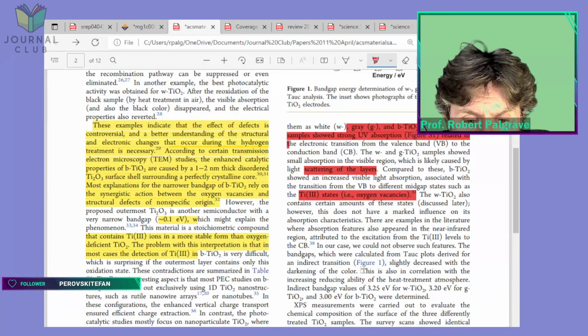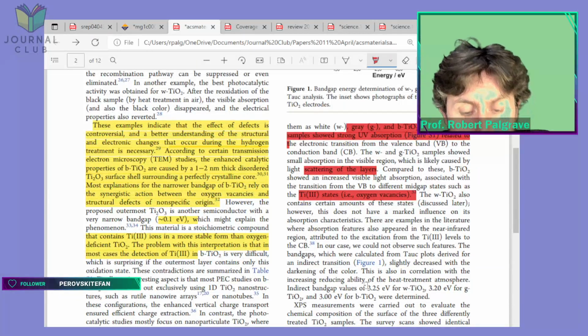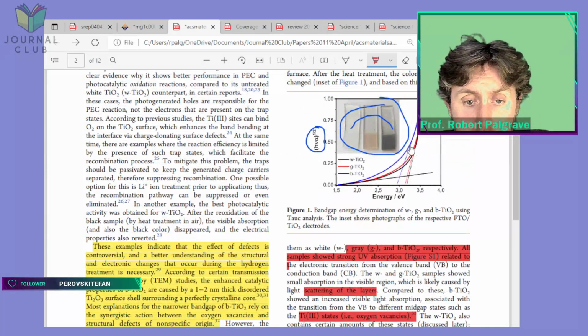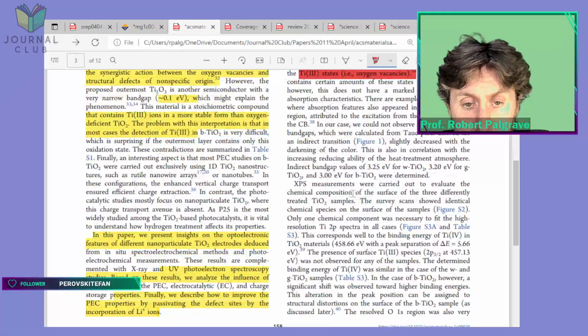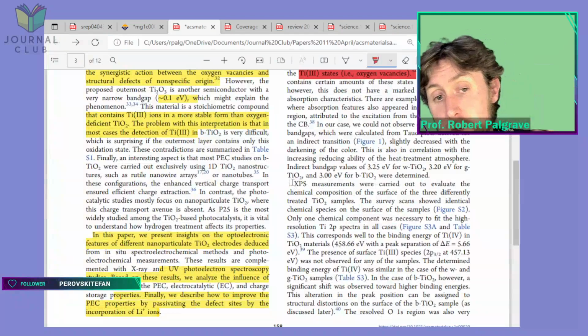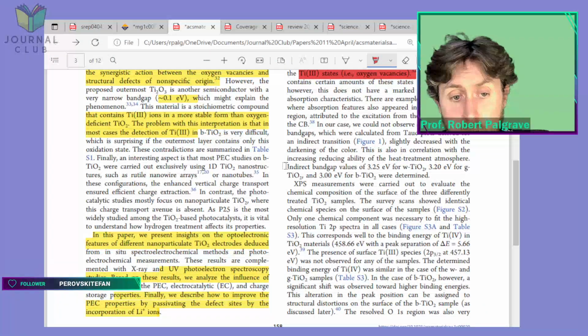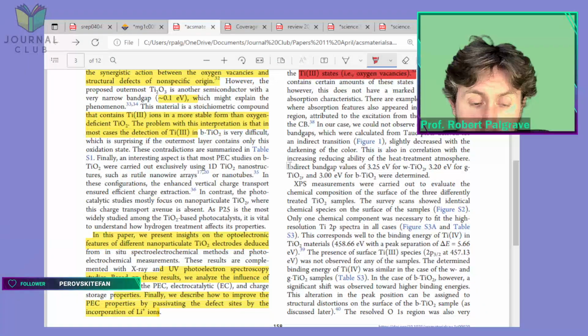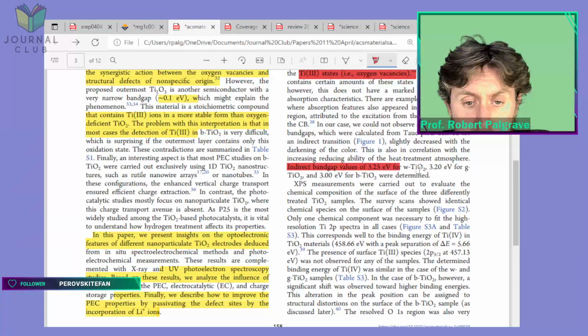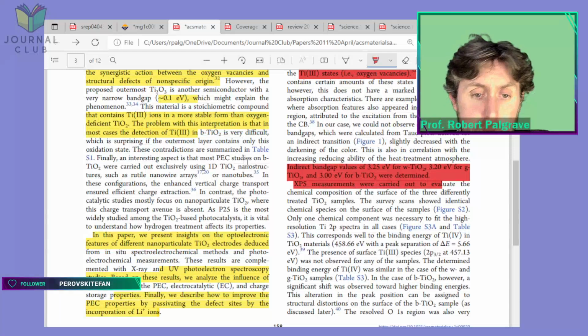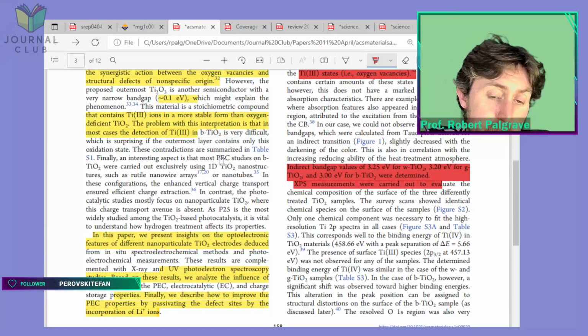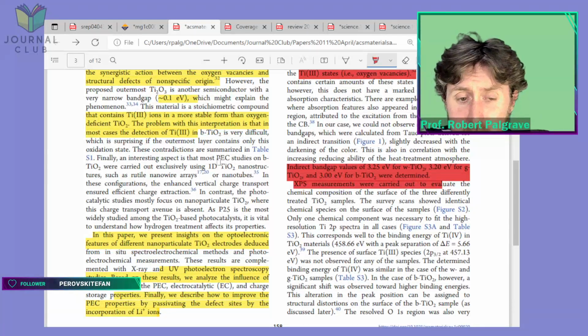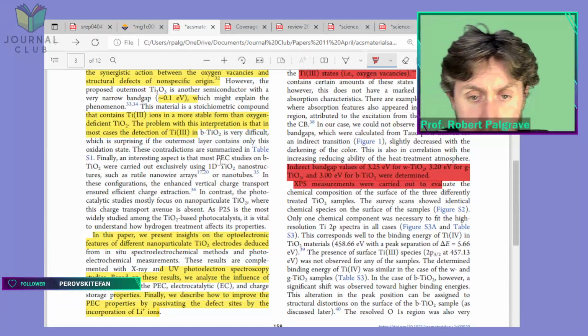So the indirect band gap values, that's the band gap values they've obtained from this Tauc plot here, extrapolating these lines down. So they've used an indirect band gap calculation method, which again you might argue whether that's the most appropriate thing to do. TiO2 rutile I think is certainly a direct band semiconductor. Anatase I think is almost direct. I think there's a very slightly lower energy indirect transition.